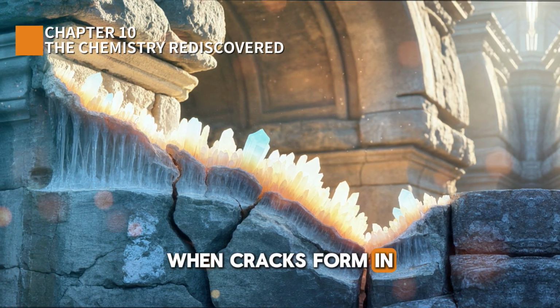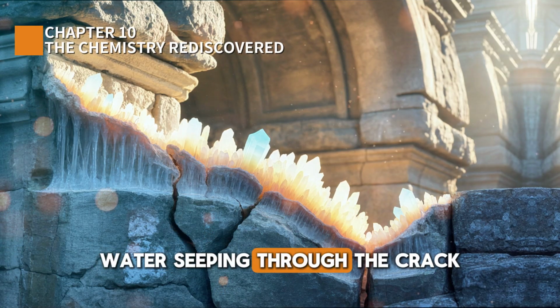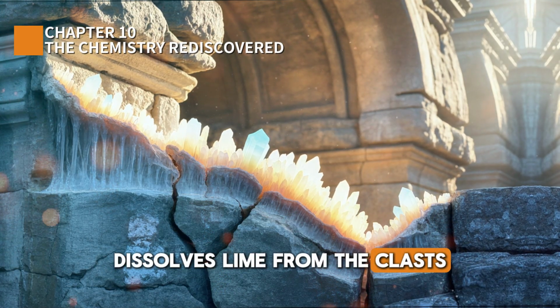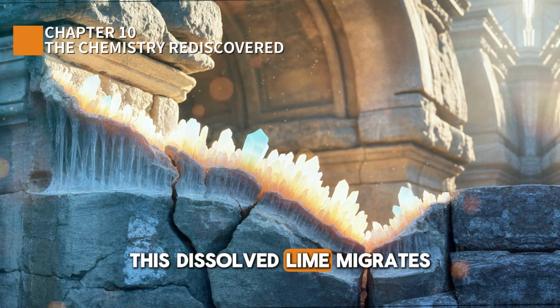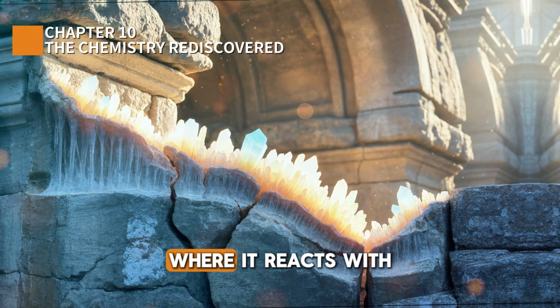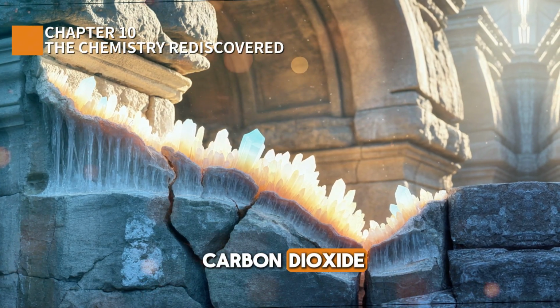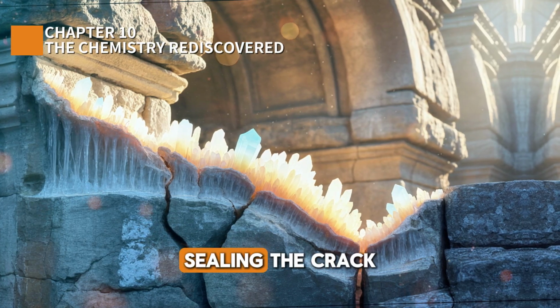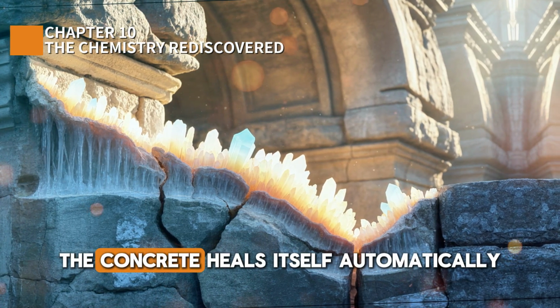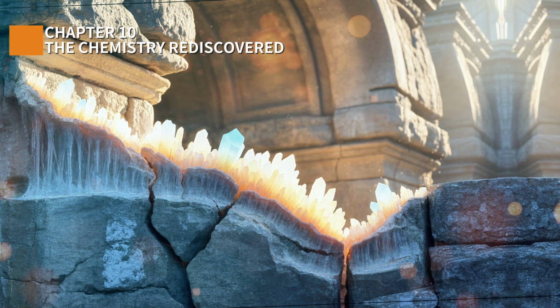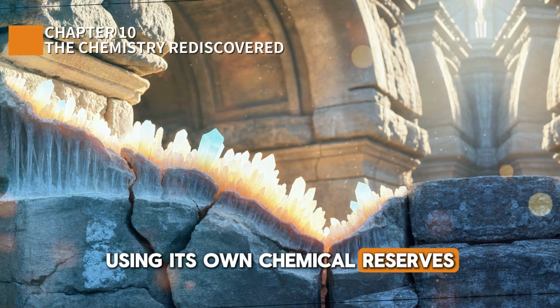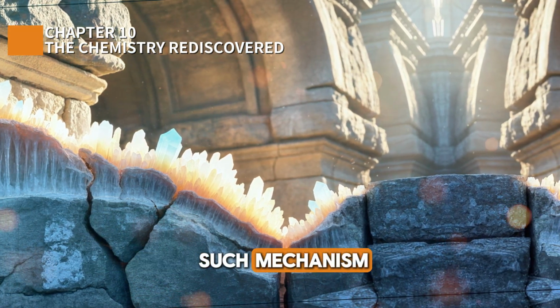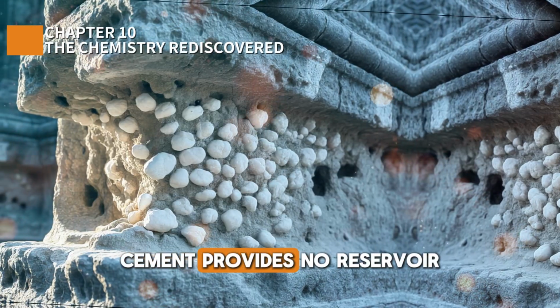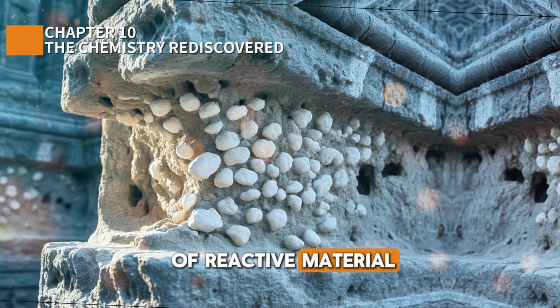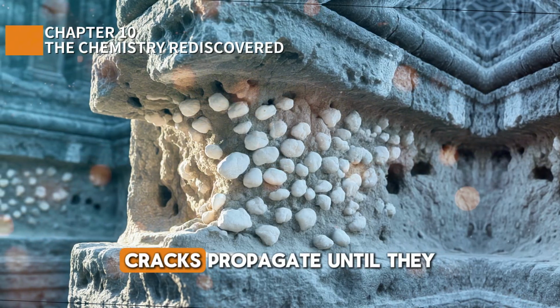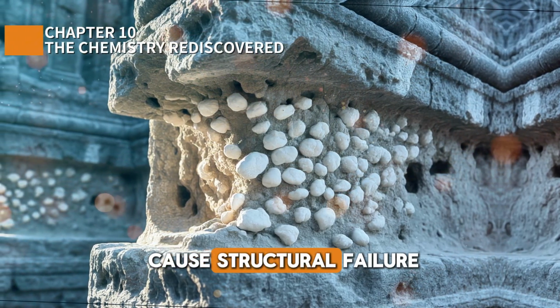When cracks form in Roman concrete, water seeping through the crack dissolves lime from the clasts. This dissolved lime migrates to the crack surfaces, where it reacts with carbon dioxide to form calcium carbonate, sealing the crack. The concrete heals itself automatically, using its own chemical reserves. Modern concrete has no such mechanism. Portland cement provides no reservoir of reactive material for self-repair. Cracks propagate until they cause structural failure.